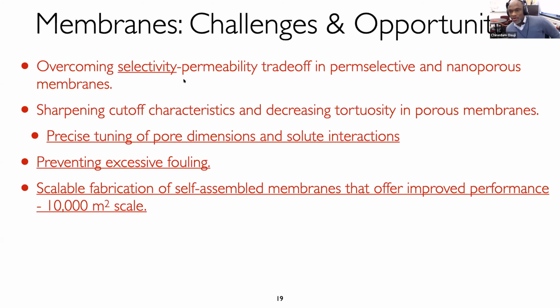So what are the challenges and opportunities? Well, the first is the one that I just highlighted, overcoming the selectivity permeability trade-off, both in perm-selective and nanoporous membranes. And I've highlighted selectivity here because in many cases, it's the selectivity of the membrane that's the limiting factor in terms of its energy footprint, and not the permeability. Okay, this is true in reverse osmosis. It's true in organic solvent nanofiltration. It's true in a broad variety of membrane processes. Sharpening the cutoff characteristics and decreasing the tortuosity in porous membranes. So these are two challenges that speak directly to improving the selectivity and potentially surmounting the selectivity permeability trade-off.